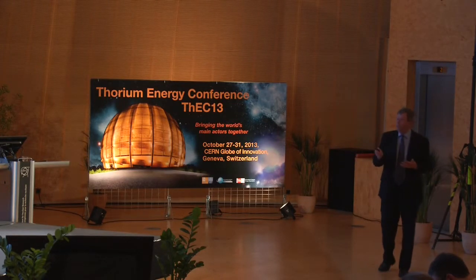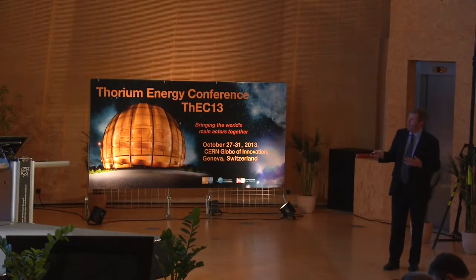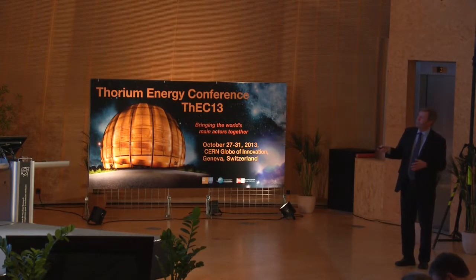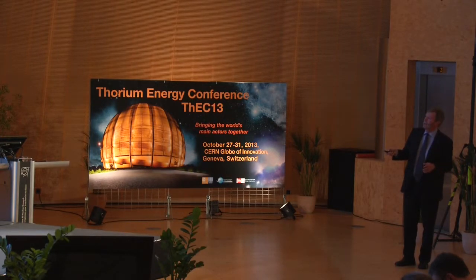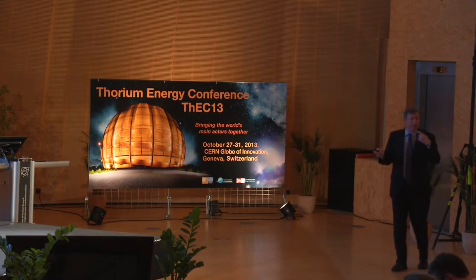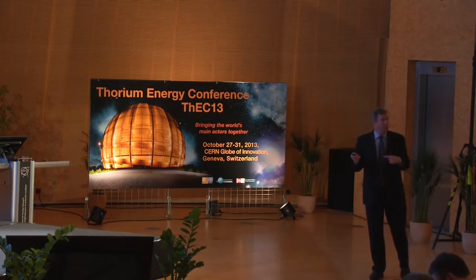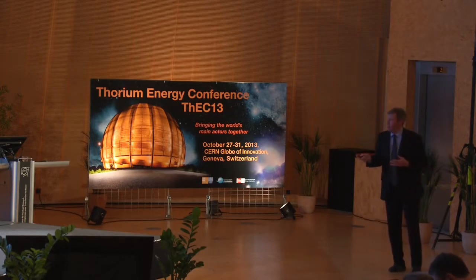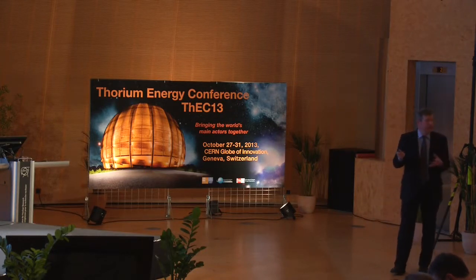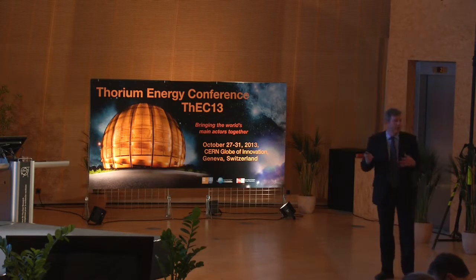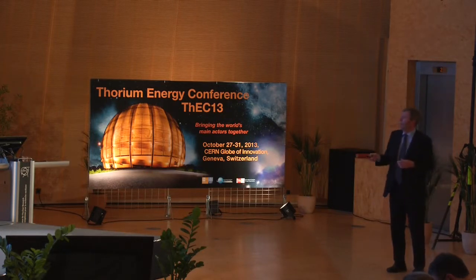And then you can go on and make predictions. So this line here represents the freezing line of the lithium fluoride, thorium fluoride mixture as a function of the composition. And these are predictions of the viscosity across the full useful range. You can see that the fluid starts to get pretty viscous when you get down close to the eutectic composition there. And so remembering how rapidly that fluid was being cycled in my reactor, you might well want to stay away from this point in the interests of maintaining good flow properties and avoiding turbulent regimes.